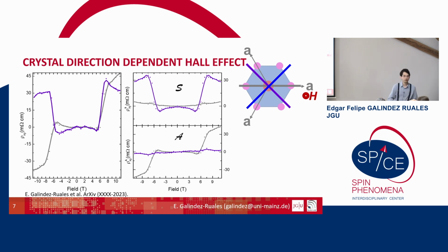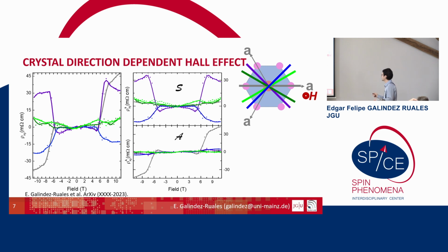So we repeat this experiment with other angles, and when we pattern along another a direction, we have a similar graph. When we pattern along 45 degrees, we have the blue one, and when we have minus 45 degrees, we have the purple one. They are similar colors because this is just a mirror reflection. So we were expecting that mirror reflection. Well, Libor was expecting that mirror reflection. I was just really confused about what we were measuring. And when we measure between these two angles, between the fully symmetric and the fully antisymmetric signal, we have almost null signal. So you have an almost cancellation of this anomalous Hall effect.